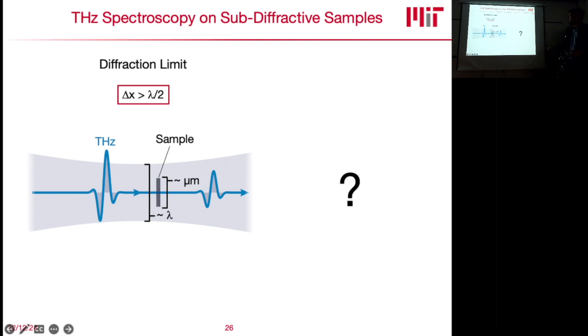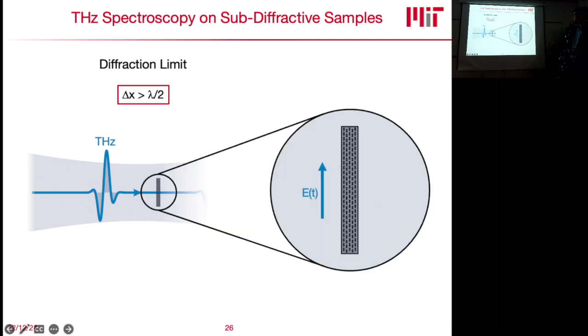So this is a very, very exciting question. And actually what happens now is, in this situation, you basically have a constant electric field applied across, or like a homogeneous electric field applied across your sample if it's much smaller than the terahertz spot. And what actually happens now is that your boundary conditions and the boundaries of your sample become incredibly important, because you have to consider the current that is driven. For example, if you now apply an electric field and you displace your electrons, it has to be conserved and has to be zero at the boundaries, right? You can't just take your electrons and take them out of your sample. So this is one boundary condition.